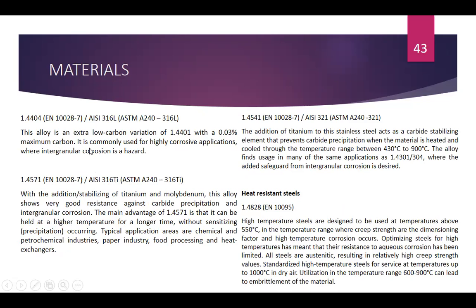Low carbon naman, with 0.03% maximum carbon. It is commonly used for highly corrosive application where intergranular corrosion is a hazard. Next, 1.4571 or 316Ti. With the stabilizing addition of titanium and molybdenum, this alloy shows very good resistance against carbide precipitation and intergranular corrosion. The main advantage of 1.4571 is that it can be held at higher temperature for a longer time without sensitizing precipitation occurring. Typical applications are chemical and petrochemical industries, paper industry, food processing, and heat exchangers.